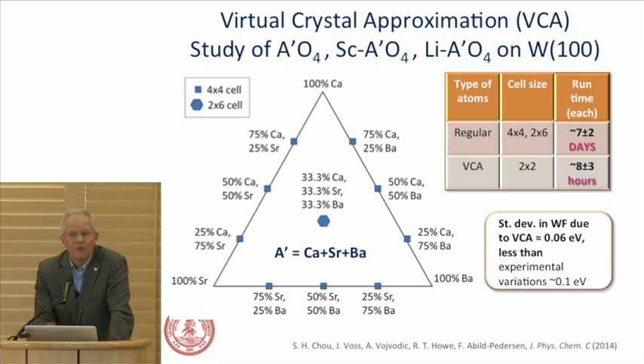Well, Sharon Chow, my first student who has not gone into a bunny suit into the nanofab in my entire career, though an EE, looked at basically doing it brute force with the actual atoms and expanding the unit cell. And this leads to around a week runtime. The virtual crystal approximation shrinks the cell, and you get down to hours. And in fact, the differences in some test cases are rather minimal. So there's an incentive to just get started.